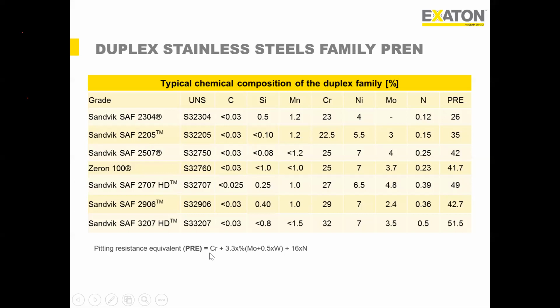Okay, and I put the formula here. We calculate based on the chromium, 3.3 times moly plus 0.5 tungsten and 16 times nitrogen. Okay, here I want to stress more on this particular formula. You can see here the nitrogen is a very important alloying element in the duplex family. Although the composition is only 0.15 or 0.25, 0.23, the relative effect on the pitting resistance is not only this much. It has a 16 times effect. So remember this: even if 1% nitrogen is lost during welding, the effect on the pitting resistance is not 1%, it is effectively almost a 16% effect. So that's why nitrogen plays a very important role in any duplex family.